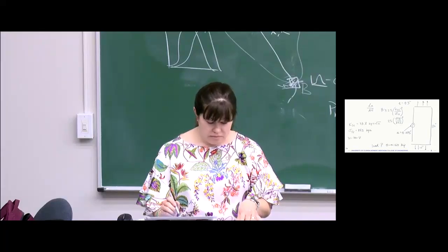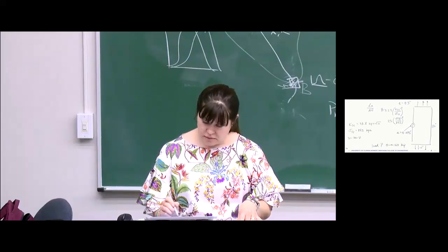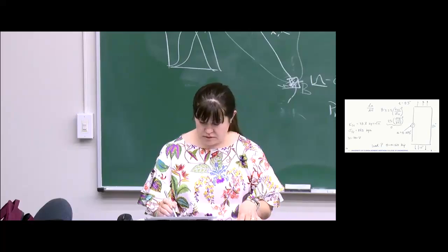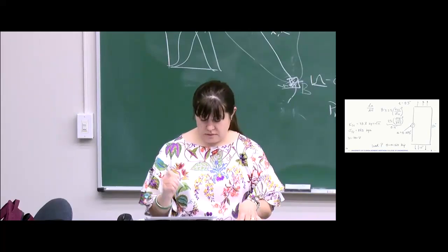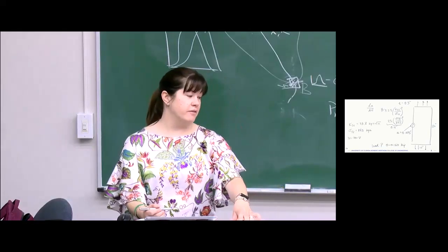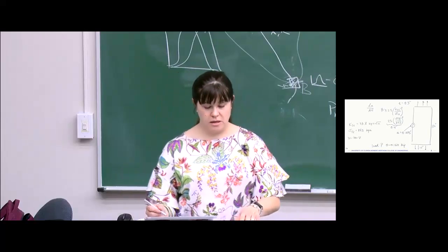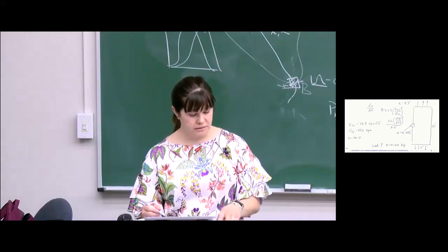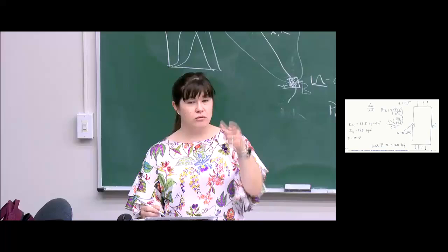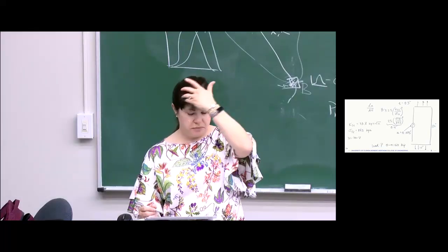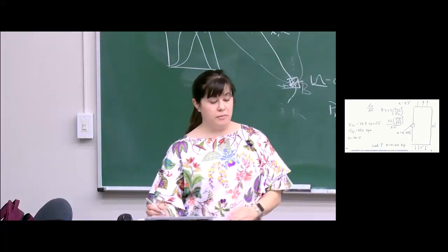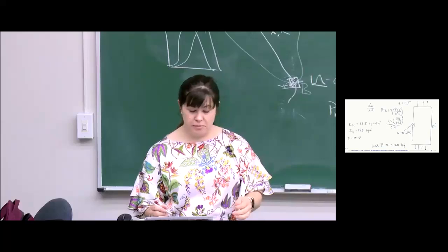So anyway, if we do this math, we come up with 0.4 inches. So our plate is 0.5. So we can use plane strain formulas here. So we don't have to correct and make it a plane stress problem. If you don't know what I'm talking about, just take my word for it. It's going to help you on the problem set.